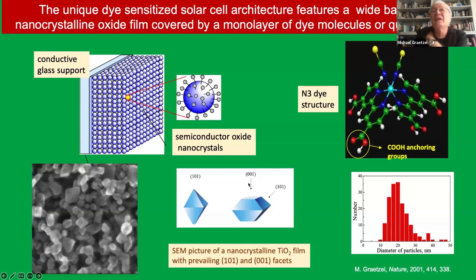And so then by dip coating, we would cover this nanocrystalline array with a dye like the standard, the N3 dye, named after Dr. Nazeeruddin, who was a postdoc at that time in our laboratory. And yeah, same anchoring groups that Goodenough had used, but the dye was not the same structure. This was much better in visible light absorption.